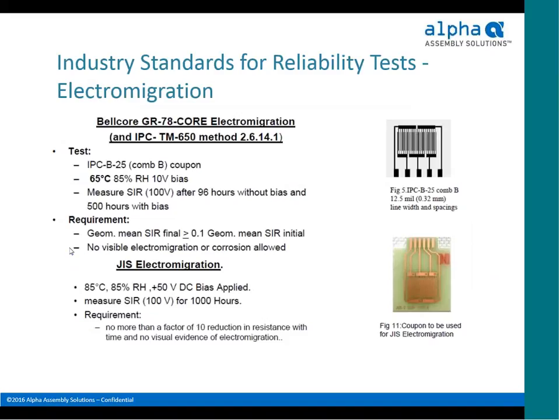JIS, theirs is 85 C, 85% RH, 50 volts DC. You measure SIR for 1,000 hours, and again, no more than a factor of 10 reduction in the resistance with no visible indication of any electromigration. So again, you have your resistance test, plus you have your visible inspection afterwards for any evidence of corrosion in these types of tests.